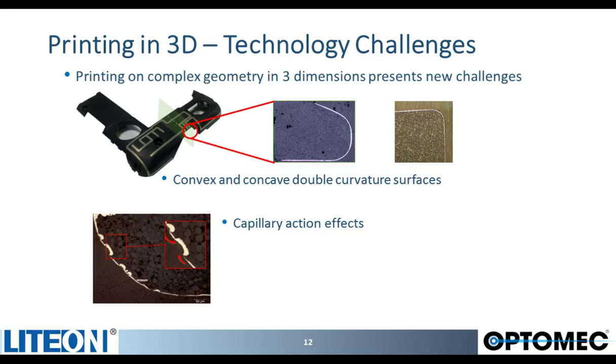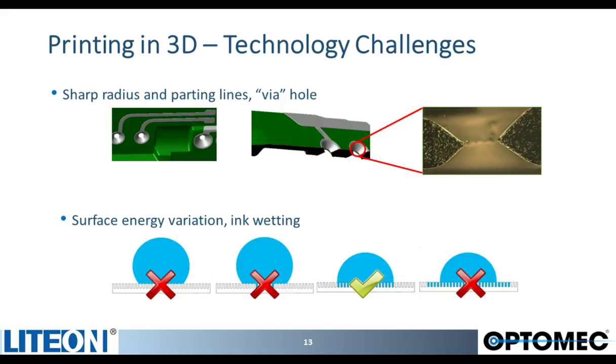And with our long experience of in-house molding as well as tooling, we are in the right position to get the best quality substrate for the printing. And this is really needed for this kind of product. Further, on the molded structure, there are always parting lines from tooling, and when traces are to be printed over these, it creates challenges. This is especially difficult for an electrical via design.